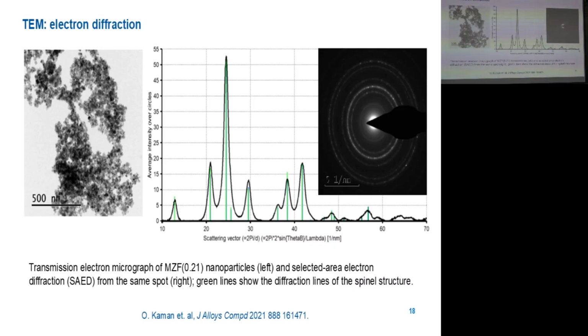Of course, you can also measure electron diffraction. Like we saw the X-ray diffraction, so this is a very analogous experiment. In this case, you can see a large area covered with particles or with their agglomerates, and the measurement of electron diffraction over the whole area. So you will collect such circles, and when you integrate the circles, you can convert it to the pattern which is analogous to the powder X-ray diffraction, and you can see again the clear pattern of the spinel structure, and in this case it was the manganese zinc ferrite, so it makes sense. And this will again show the crystallinity of your sample, and you can also consider measuring electron diffraction on a single particle if you have some nice microscope. So then you can do analysis for a single particle.